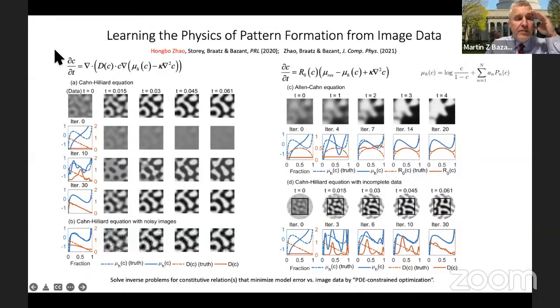So on the left, we see the Cahn-Hilliard equation I mentioned before for a certain kind of model that has a homogeneous chemical potential, like I showed you before, this kind of non-monotonic thing, like this blue curve here. That's the dashed, the actual true model. And then C here is the concentration field, and D of C is an unknown diffusivity versus concentration, which in this case is 1 minus C, just a linear dependence. So at the top line here, we show a simulation of phase separation according to this model. So if you start with a 50% mixture with some fluctuations, it then evolves into these snake-like patterns of high and low density stable phases, in this simple model.